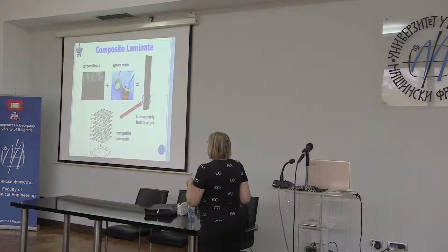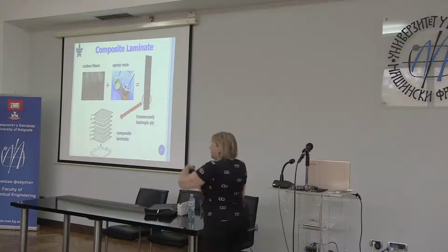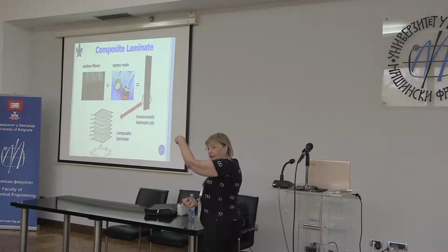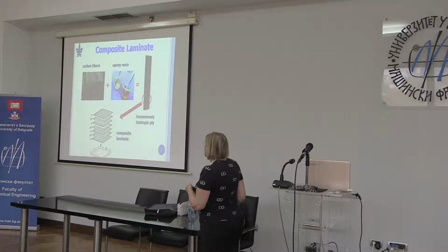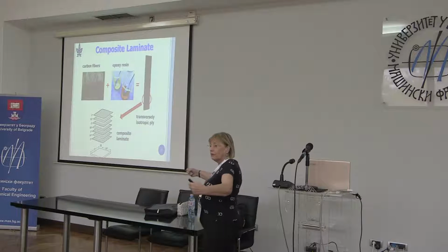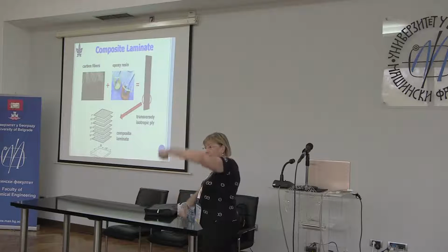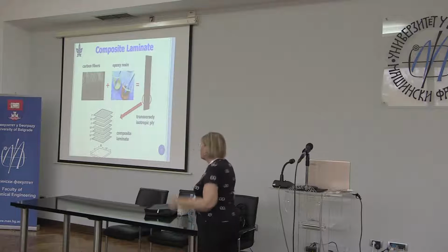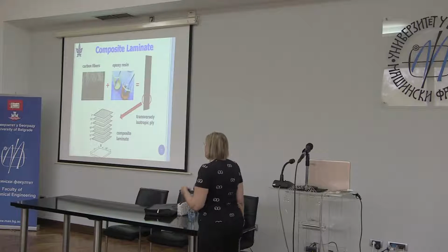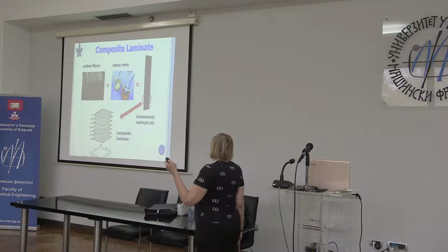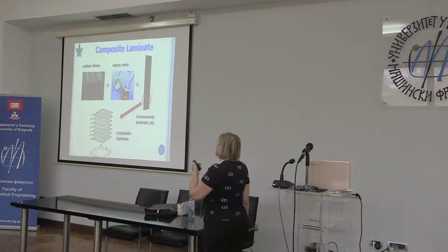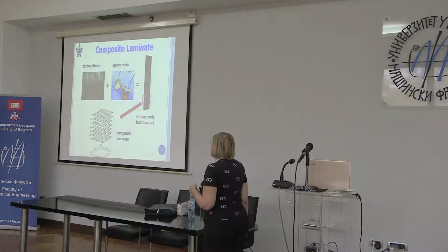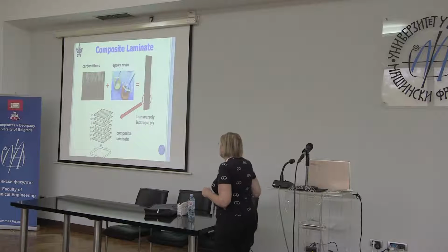So if we have all the fibers in this direction, and I pull on it in that direction, it's very stiff because the carbon fibers have very high Young's modulus. If I pull on it transverse, it's very weak. So E in this direction is different from E in the longitudinal direction. So there are 5 properties: E1, E2, G12, nu12, and nu23, and then you have the transverse G, which is related to E and nu.